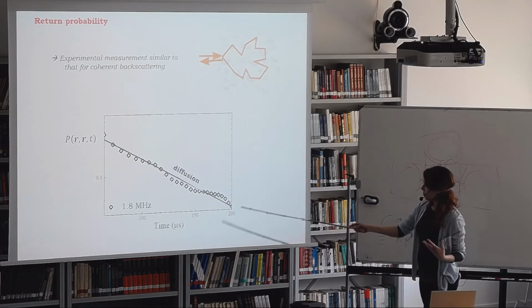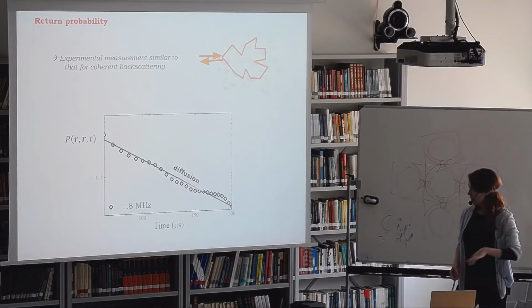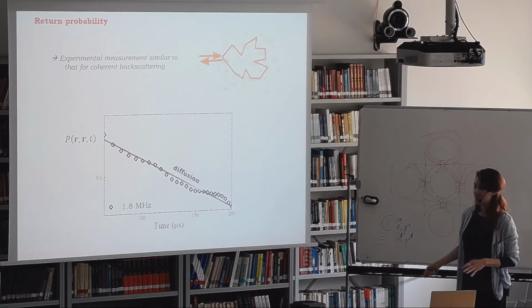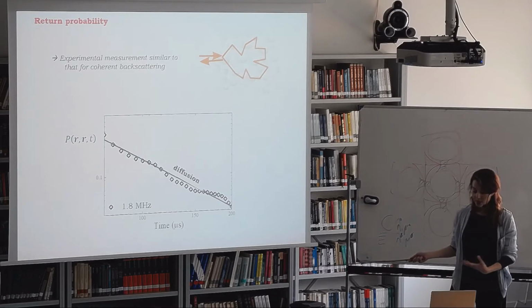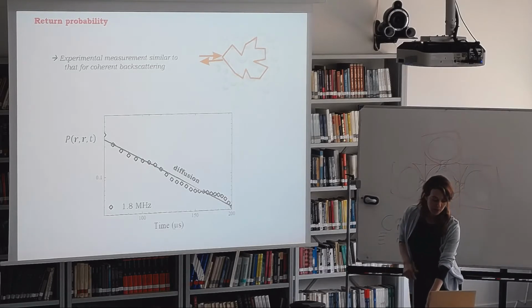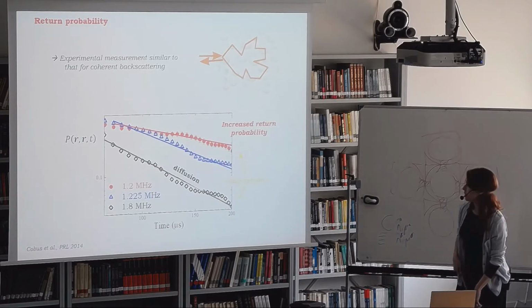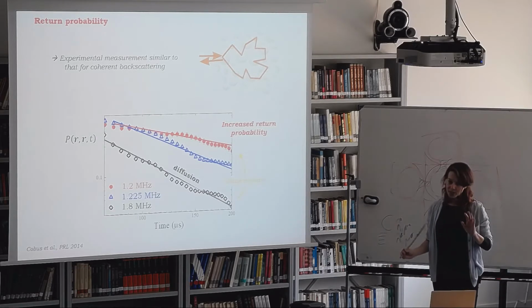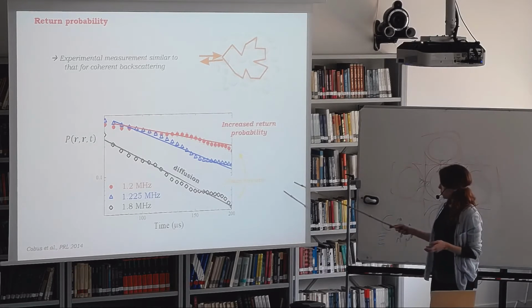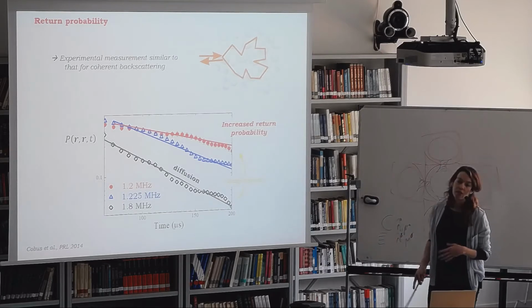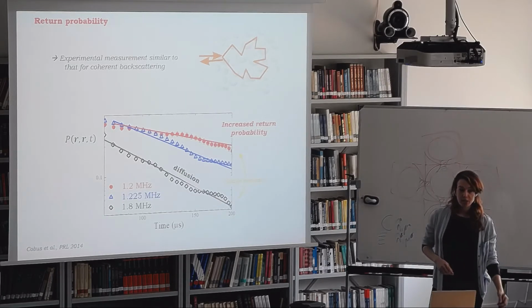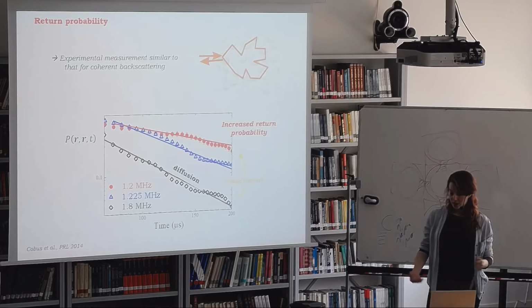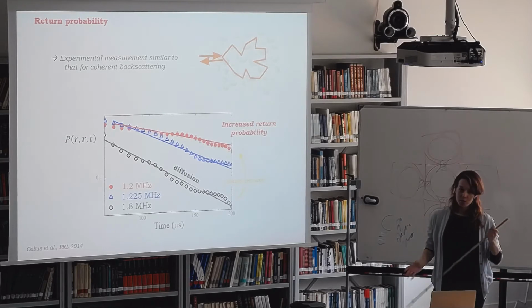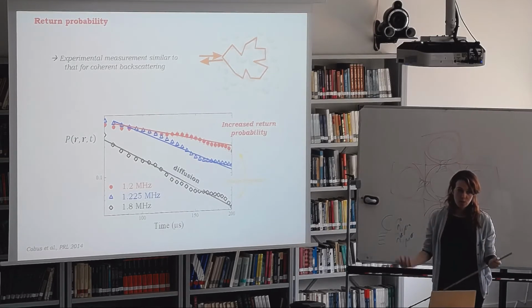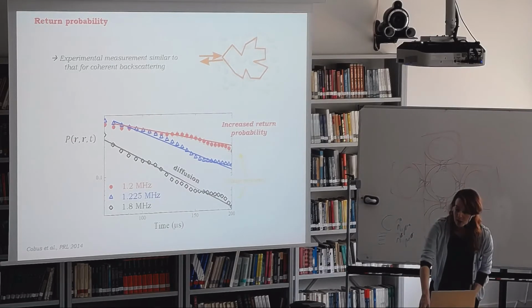So we can plot this as a function of time. It decays as a function of time. In the diffuse regime, we already have predictions that tell us what should happen, and they fit quite nicely to the experimental measurements. Then we see that at these same special frequencies where we have anomalous behavior, the return probability increases. So we're observing what we had previously sort of intuitively predicted. The return probability is increasing, the waves are coming back to the same spots again and again, and diffusion is becoming renormalized.